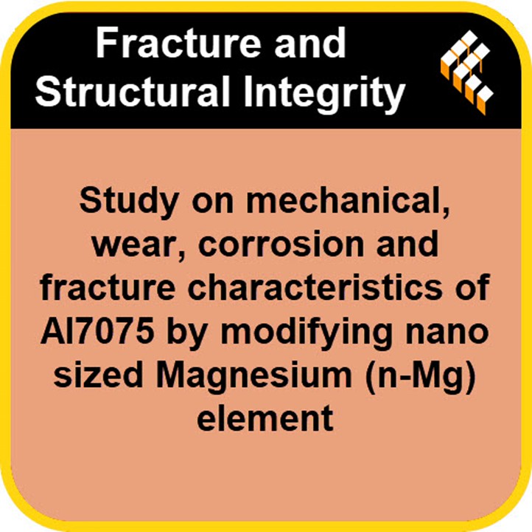But before we write this whole thing off, there was a clear counter victory in the durability section, right? Wear resistance. Yes, the wear results were extremely positive. They showed an 18.82% improvement in resistance. Which is great. And this ties right back to the increased hardness we talked about. It follows Archard's law: wear is generally inversely correlated with hardness. The finer grain size and the rigidity of the modified alloy made it far better at resisting surface loss from abrasion and friction.